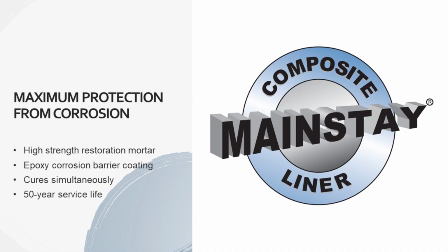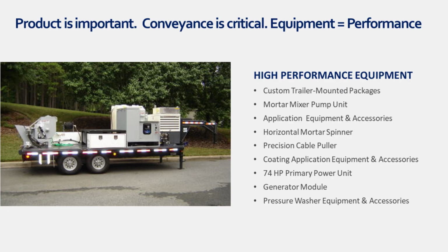If you get into a very highly corrosive area, there's nothing better than a top coat, such as our mainstay composite liner. You're going to go through and put your cementitious on the pipe, but if it's highly corrosive, you're going to want a barrier, which is our epoxy. So we go in there and spray it with epoxy, and that's your best corrosion protection.